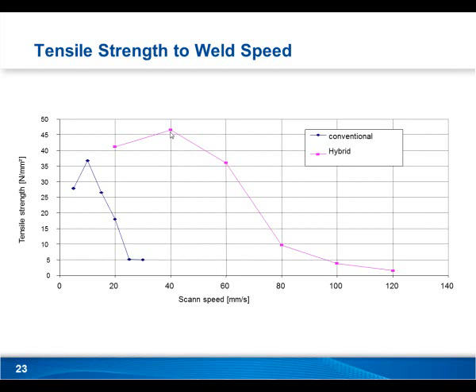As you can see here, this is 40 millimeters per second, about 60 millimeters per second, but in typical production environments, the laser will be traveling at about 80 millimeters per second. And that equates to about 30-second cycle times, maybe less depending on the size of the taillight.